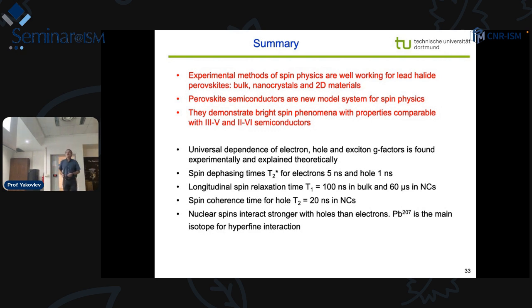So this is a summary of my talk. My main goal was to convince you that experimental methods of spin physics work well for lead halide perovskites, bulk crystals, nanocrystals, and two-dimensional materials. Perovskite semiconductors are really new model systems for spin physics. These materials demonstrate very bright spin phenomena, with parameters very much comparable to the III-V and II-VI semiconductors which we have studied so far. In some sense, they go beyond. The typical spin relaxation times which we observed are very comparable to what is known for the III-V and II-VI nanocrystals.